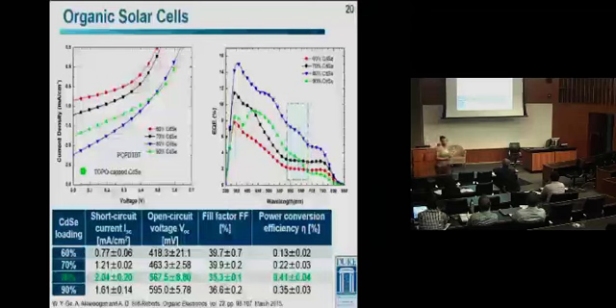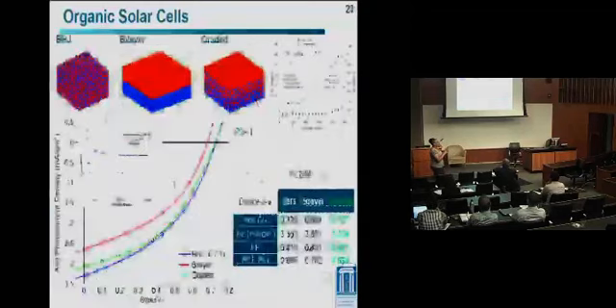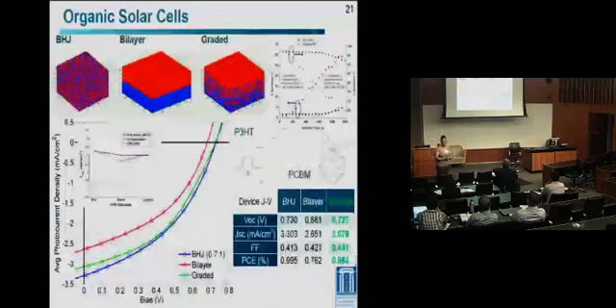One thing that's exciting about the MAPLE, while our device efficiencies are still much lower than what you get from the solution-based deposition, is that we have the capability of doing unique heterostructures and designs. One example is tandem structures. We're not limited by the solubility of existing layers. Another is being able to change the active region structure itself. As opposed to the bulk heterojunction, which people do, we can do something like a graded layer, where you change gradually the composition from the polymer to the small molecule as you go through the device.